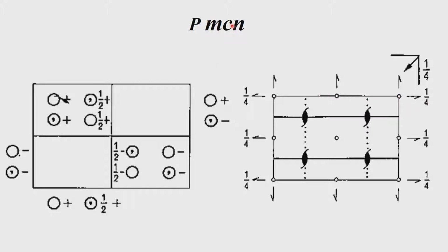Remember, this is 2/m, 2/c, 2/n, and with our knowledge on the way in which the symmetry element moves away from the origin when we have translation involved symmetry operations, this actually now represents the mirror at 1/4 along the A direction. So, the mirror plane is normal to the A direction and it is removed by 1/4 in this direction.